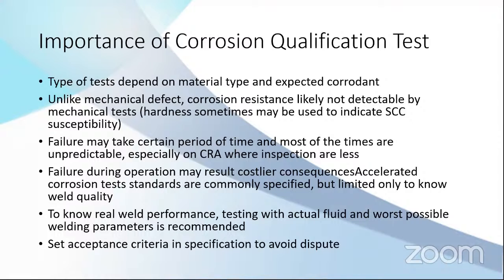And always set certain criteria during the corrosion test, so as to avoid dispute between the fabricators and the users. Normally the standard doesn't provide certain criteria. They just provide the test method. But you need to set the criteria before the test. For example, there should not be pitting at 40 Celsius. You need to set it in the test requirement. If you don't set it, then the result can be disputed. The fabricator can say at 30 Celsius you don't have pitting, so it is good, but what you really want is 40 Celsius. But it will be disputed. It will be messy. So it's always better to state the acceptance criteria.